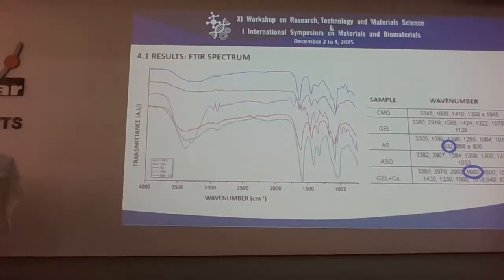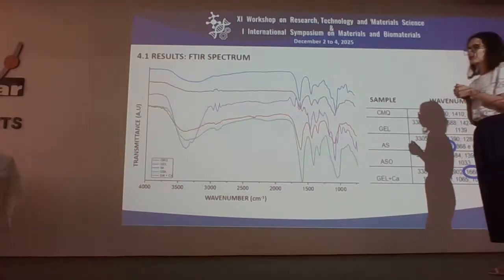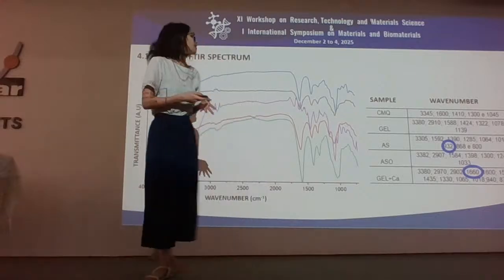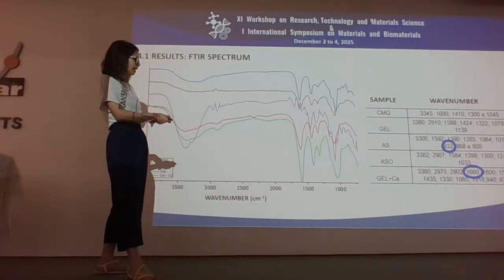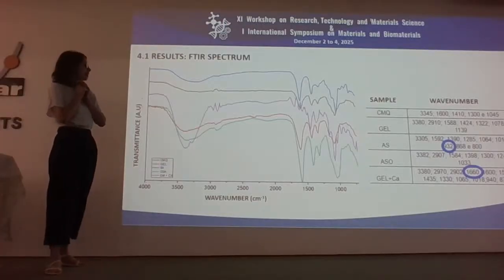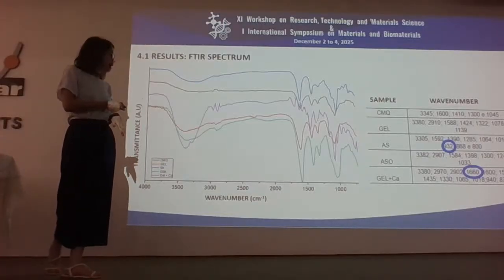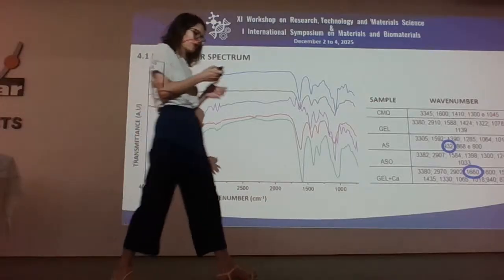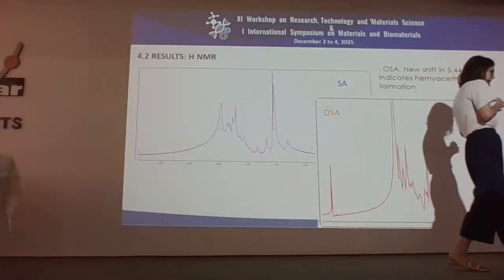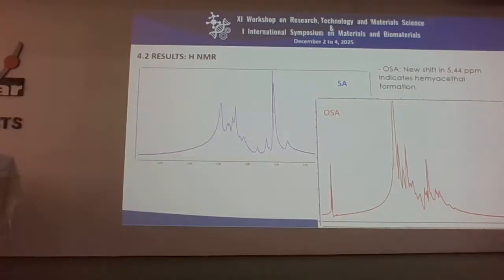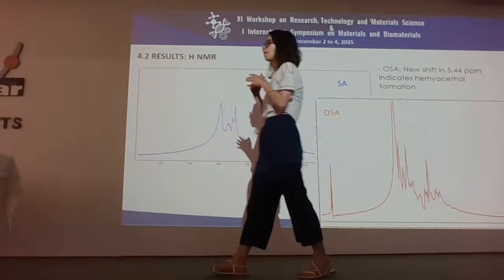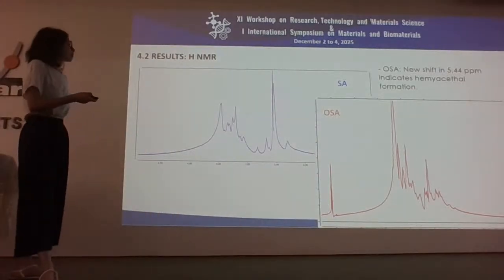Well, the FTIR spectrum showed two most important things. The disappearance of this peak in oxidized sodium alginate could prove that the oxidation really occurred, and the appearance of this peak at 1660 showed that the imine bonding was formed. So, NMR analysis showed a new shift at 5.44, and it indicates hemiacetal formation, and it's related to the appearance of new peaks in sodium alginate.